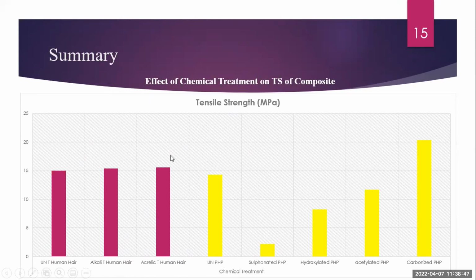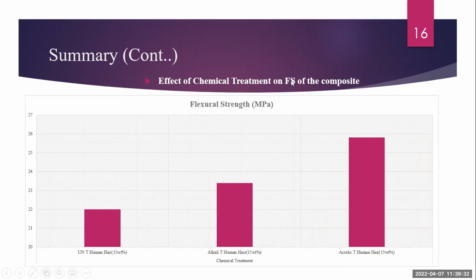So what I can summarize of the whole work: the effect of chemical treatment on tensile strength. We can see that untreated human hair fibers used to form a composite give less result than treated human fibers, but the improvement is slightly very much less. Here again, pig hair powders were also used in some scientific work, and they found that the treatment of hydroxide acetylate is very much less effective compared to carbonized pig hair powders used for the fabrication of composites. Effect of chemical treatment on flexure strength.